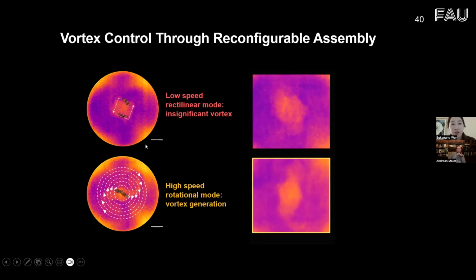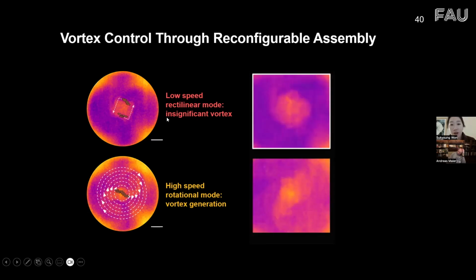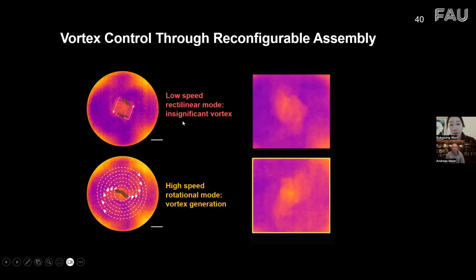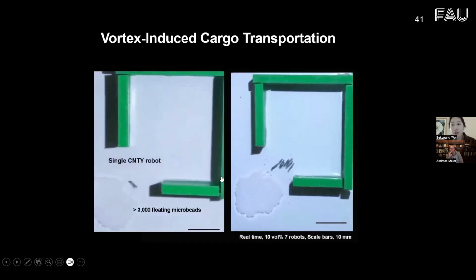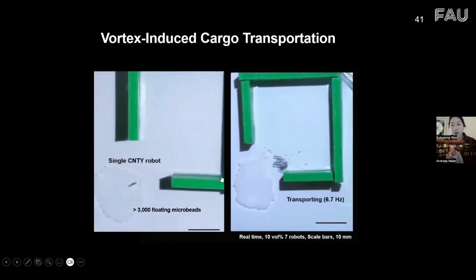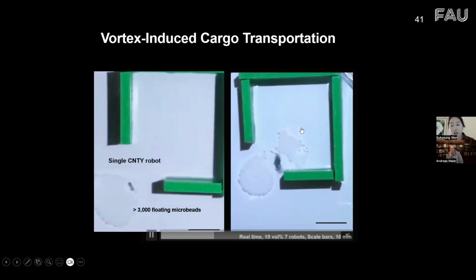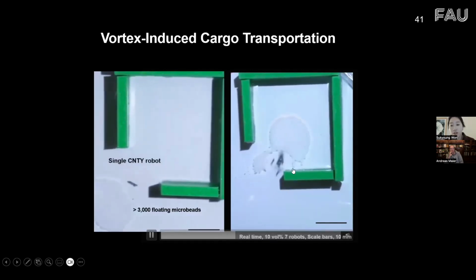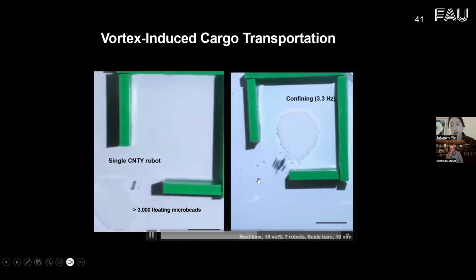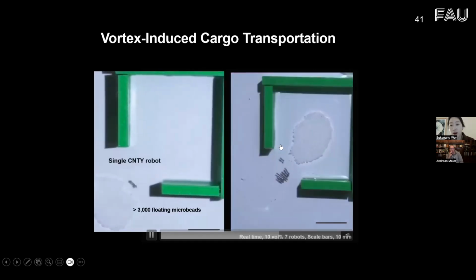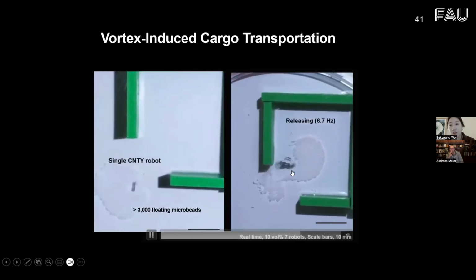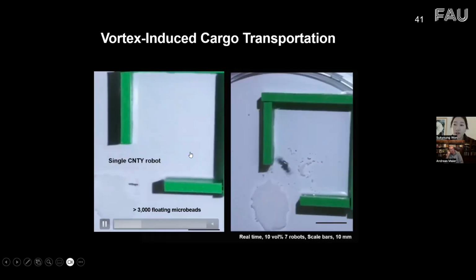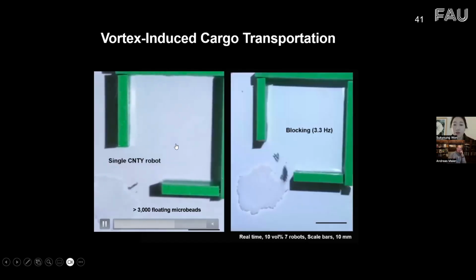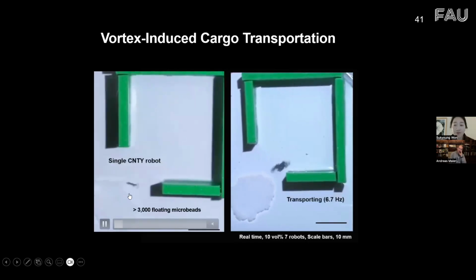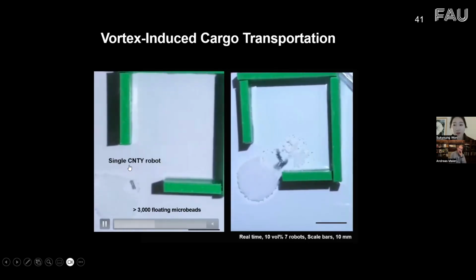So that means we could control the vortex generation. At low speed, we did not generate a high magnitude vortex, and as we increase the speed, we can generate the vortex significantly. So by using the vortex generation, we transport thousands of microbeads at the surface of the water to transport inside this space or block this transported microbeads by applying the rectilinear translational swimming. And also this block of microbeads is released by changing the swimming mode. This collective behavior shows the importance of the use of microrobot swarms, because a single robot cannot do it alone, because it could not generate a high magnitude vortex.